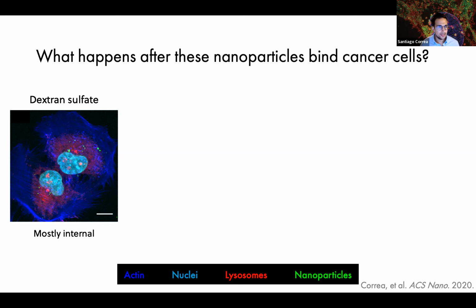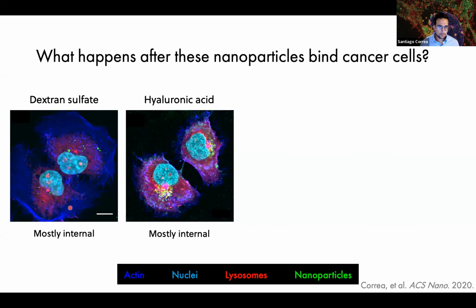And what we can see in ovarian cancer cells treated with dextran sulfate-coated nanoparticles is that at 24 hours, we see these punctate green spots within the interior of a cell, which is what you would expect to see. Generally, when a nanoparticle binds to the surface of a cell, it is quickly internalized. So when we looked at our hyaluronic acid-coated nanoparticles, we weren't surprised to see the same subcellular distribution.